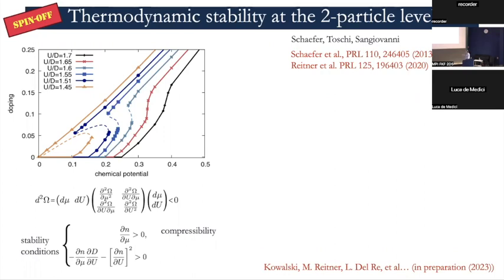But the second condition implies not only the compressibility, but also the derivative in u of the generalized double occupancy, which is the conjugate variable to u in our Hamiltonian. So we had u and j as parameters of the interaction, but j is proportional to u. So there is something multiplying u, which is conjugated to u, and we call it generalized double occupancy. This has to have a derivative in u, it has to go down in u, so it has to be negative normally. But when it's positive, then you're violating a stability condition, even if the compressibility is positive, and that's exactly what's happening in these branches over here.